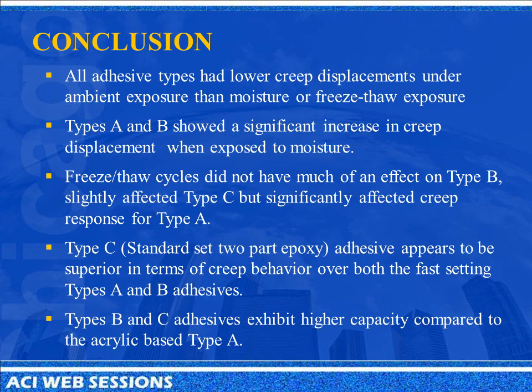Types A and B, which are the fast setting ones, showed a significant increase in creep displacement when exposed to moisture. Freeze-thaw cycles did not have much of an effect on type B, slightly affected type C, but significantly increased it for type A. Overall, type C, which is the standard set, epoxy-based adhesive, appears to be superior in terms of creep behavior over the fast setting ones, types A and B.